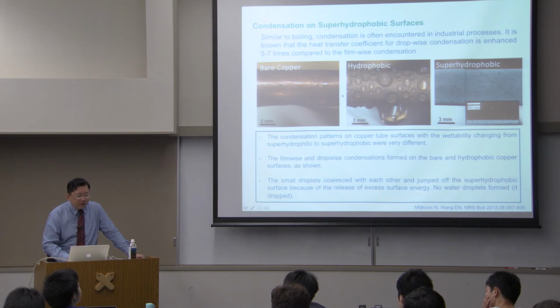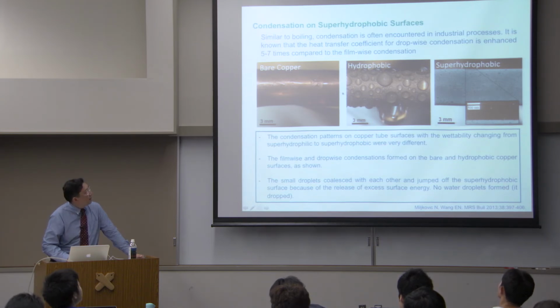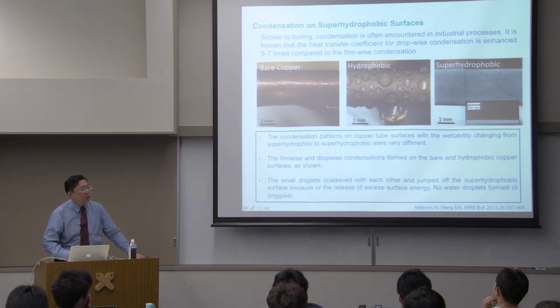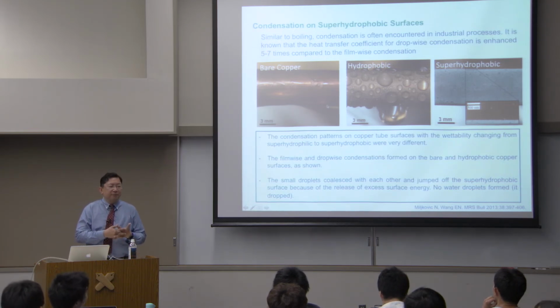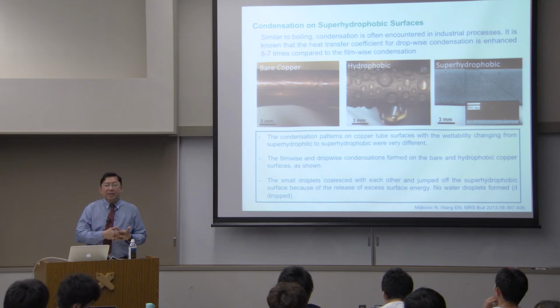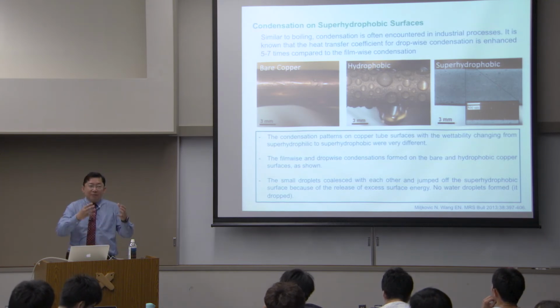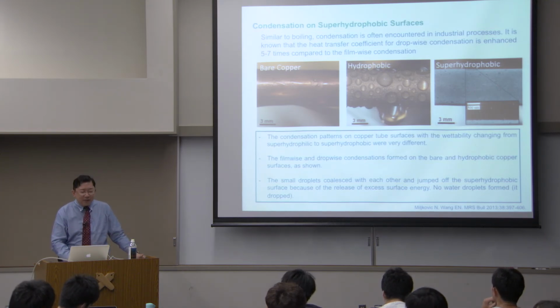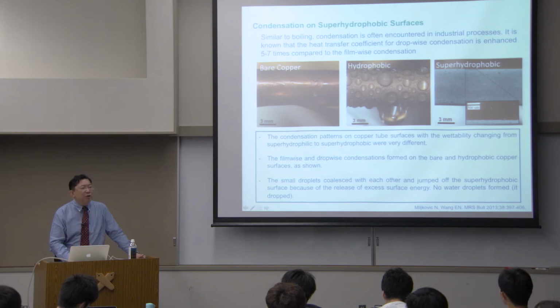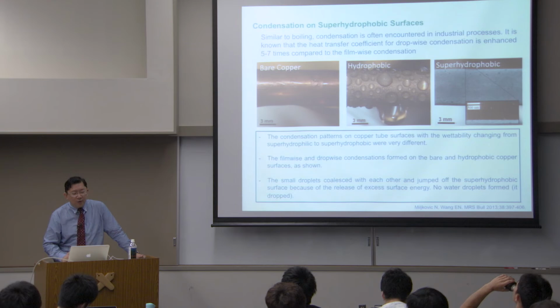So take this example: if I have bare copper, you see the liquid just coating it. What's happening to the liquid? It's not dropping off. The liquid basically forms a film, which prevents the bare copper from collecting a lot of water.